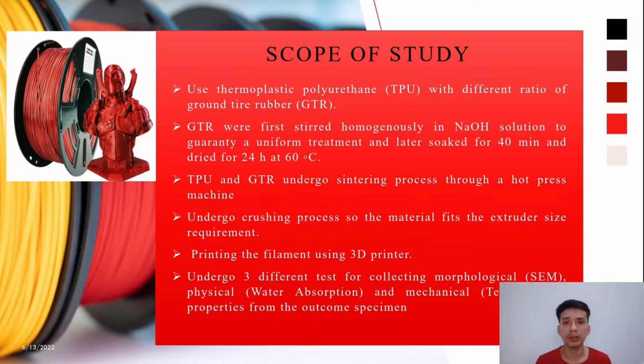printing filament. First, we use different ratios of TPU and GTR. The GTR is first treated with sodium hydroxide solution to guarantee a uniform treatment, then soaked for 40 minutes and dried for 24 hours at 60 degrees Celsius. TPU and GTR undergo a sintering process through a hot press machine. After that, they undergo a crushing process so the material fits the extruder size requirement. Then the filament is printed using a 3D printer. Lastly, the outcome specimens undergo three different tests: morphological, physical and mechanical tests.